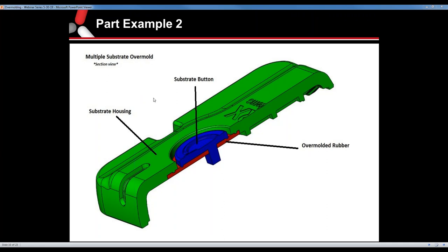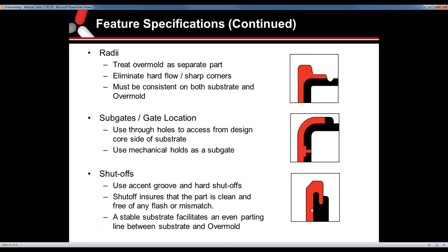Question: Can you review what makes a good shutoff feature between the substrate and the overmold? Basically, you want to avoid thin areas leading up to the part edge — definitely do not want any type of knife edge. You want a good wall thickness that butts up clean to the substrate area. Anytime you have thin or knife edges, you run the risk of flashing and the overmold peeling away. Nominal wall is key, and good radii will help the overmold process function as it should.